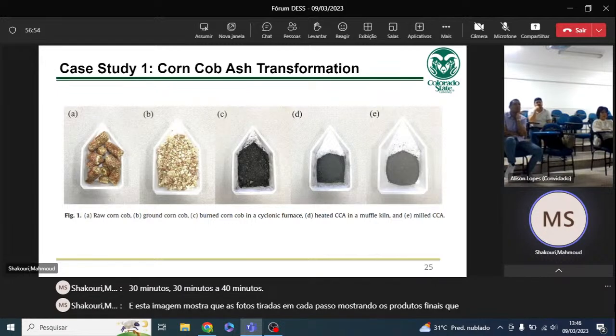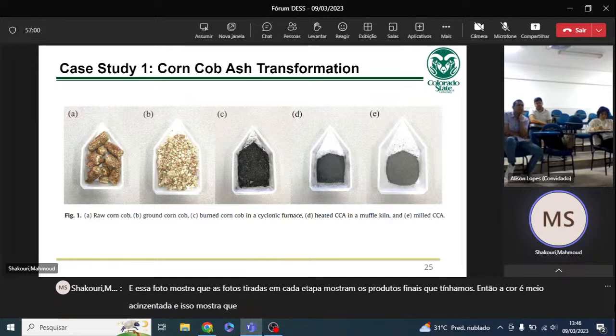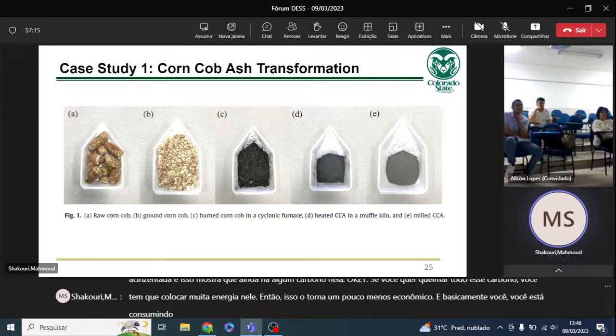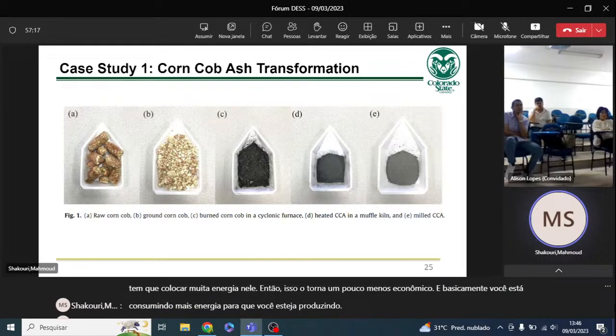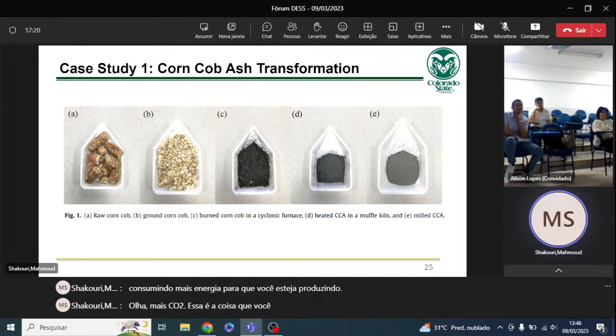So the color is kind of grayish, and that shows that there is still some carbon in it. If you want to burn all of that carbon, you have to put a lot of energy into it. So that makes it a little bit less economical. And basically you're consuming more energy so you're producing more CO2. That's the thing that you should avoid. So we were happy with this.